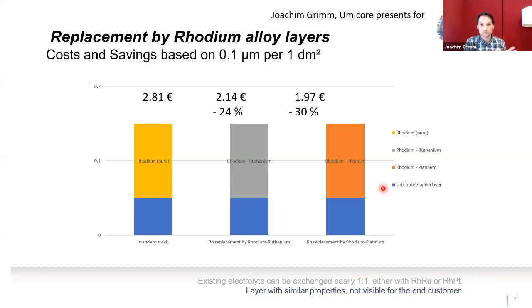So with this, it's an easy way in the plating job shop. You have your standard pure rhodium plating, but instead of this, you just change your tank or make up another solution with this rhodium-ruthenium alloy plating or with rhodium-platinum. So there's nothing specific needed. You have the same setup in your plating shop, like rectifier, wires, anodes, and so on. Small adjustments have to be done. The rectifier has to be powerful enough and proper anodes have to be used, but the setup is the same as you are used to. And you can do it either in 1 beaker, 1 liter, or you can go to 1,000 liters if you want. And then the saving will be really interesting. So this is, I say, the first level of saving you can do. This is an easy replacement of the one plating by using another plating to get this saving. The result for the client is not really visible.